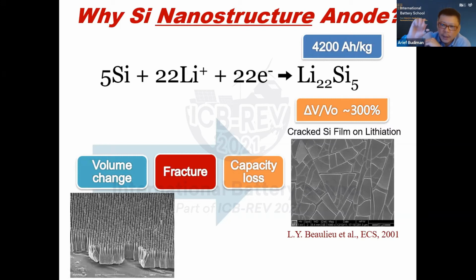In the thin film form, there is no knob. Well, we have a knob in terms of the thickness of the film maybe, but if we want 100% silicon, that's it. The thickness of the film is pretty much what we can adjust. Then you might think, okay, we might just make it very thin, but if it is very thin silicon, then obviously your capacity is not going to be much either, right? Because the capacity, or the energy density, depends on how much lithium ions you can hold. So obviously you need more knobs so that you can have enough material to hold the charges, but at the same time doesn't develop cracks. So that's what I'm talking about today.